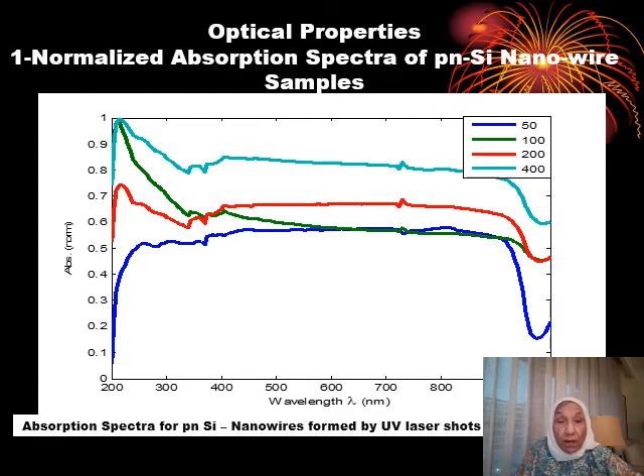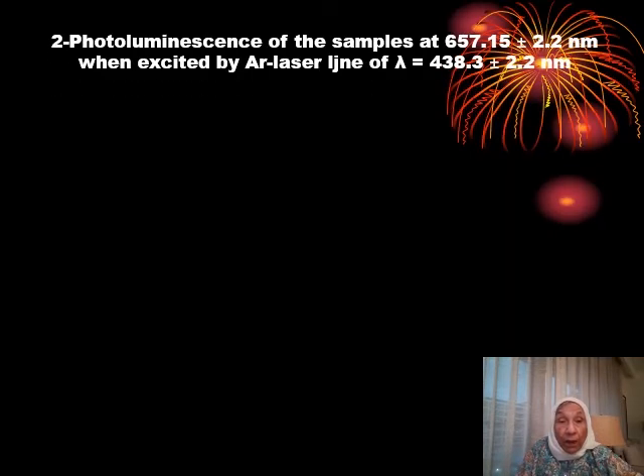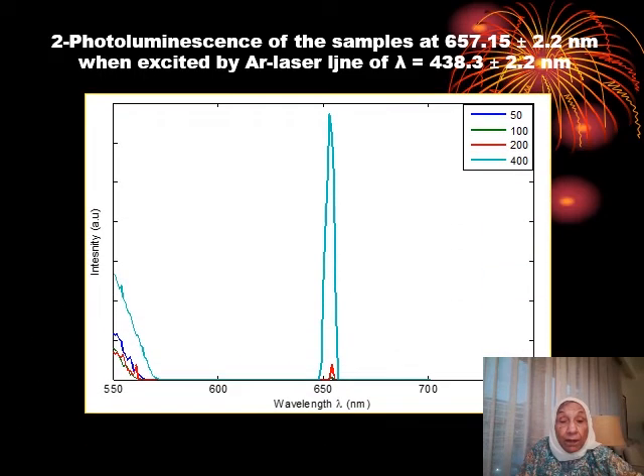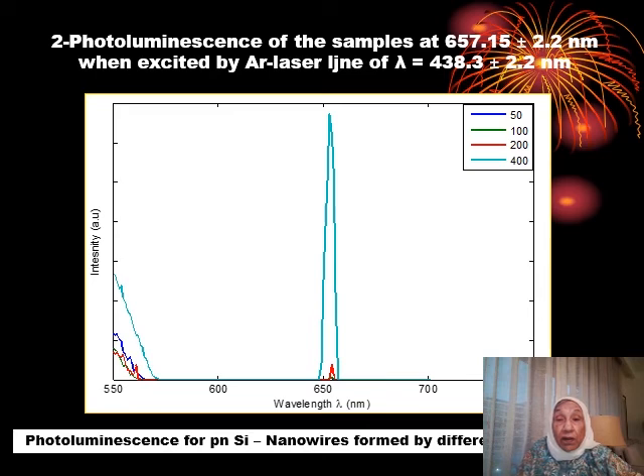So this is the optical properties, normalized absorption spectra for the PN silicon nanowire samples prepared. The photoluminescence of the samples at 657.15 plus or minus 2.2 nanometer, when excited by argon laser line of lambda 438, was found to photoluminesce on absorption of a wavelength 657, that is at the range where the conventional solar cells are actually not responding.